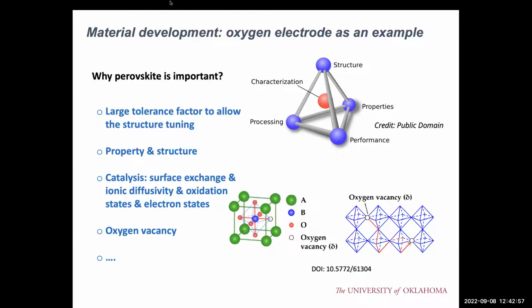Because the perovskite structure has a very large tolerance factor. What is a tolerance factor? Tolerance factor describes how the crystal structure can be distorted because of the dopant at the A site, B site, by the gas condition, by the temperature. All of these conditions and also the composition can cause distortion of the structure. But the perovskite has a very high tolerance factor. So you can dope many kinds of elements. You can dope a large fraction of these dopants into the crystal structure.